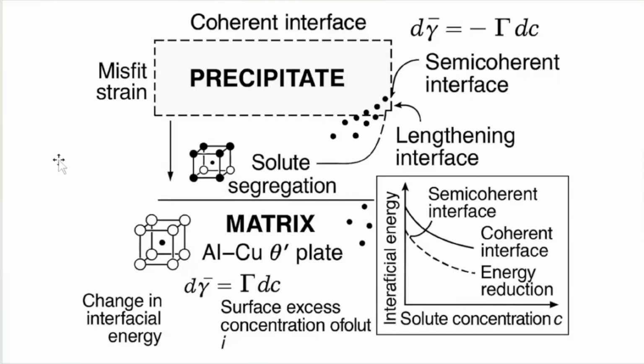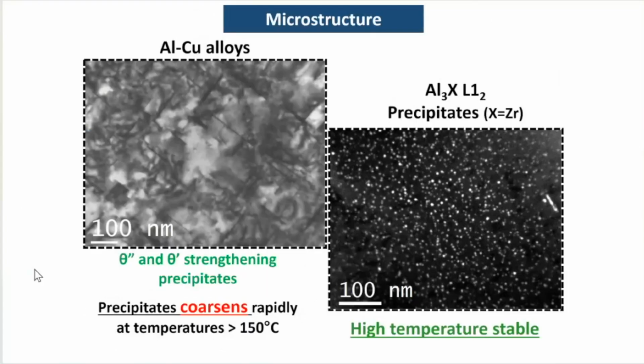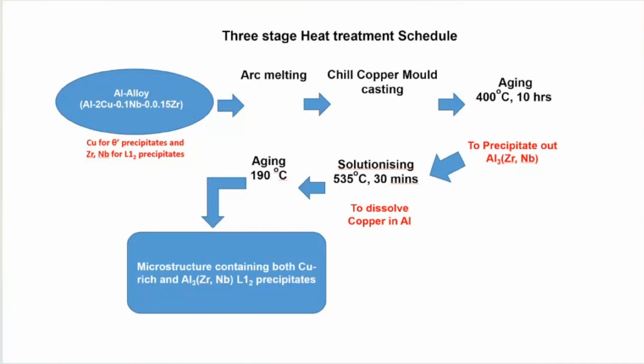Therefore, we decided that we'll combine both. We'll combine the precipitation, theta prime and theta double prime precipitates, and the ordered precipitate to strengthen the matrix and produce an alloy which hopefully will meet our goal. So we devised a heat treatment cycle. We call it a three-stage heat treatment schedule. We took aluminum with 2 copper atom percent, and then added 0.1 niobium and 0.15 zirconium to get an L12 ordered precipitate of niobium and zirconium.